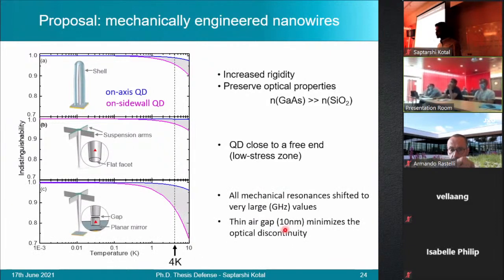And finally, a third possible solution would be to introduce a 10 nanometer thin air gap between a 200 nanometer tall nanowire section at the bottom, which contains the quantum dots, and the top taper. So the air gap is sufficiently thin to minimize the optical discontinuity, but it also helps to completely decouple the system